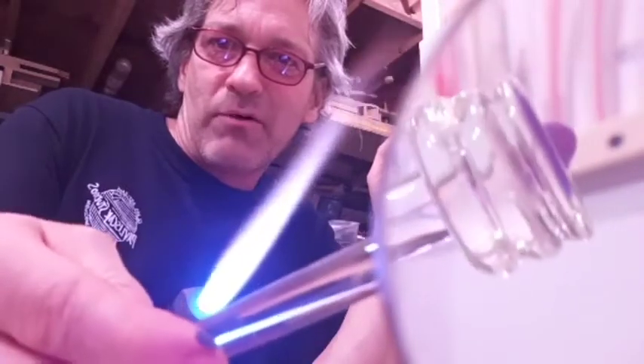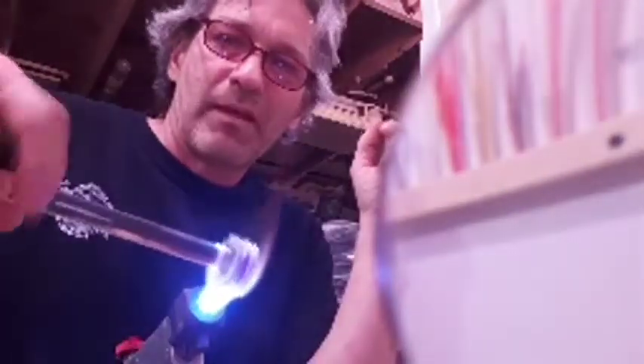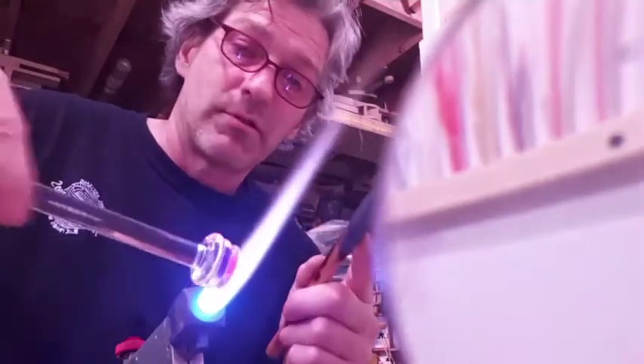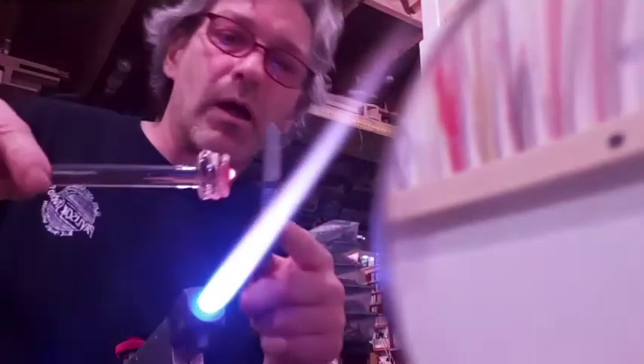And then you see it's bumped out from the surface. So let's heat it, and then I'm going to push it in a little bit, and then I'll melt it until the edge of the dot fuses with the back disc. If you press the dot in, you're chilling the area where you first hit the dot, and so it doesn't spread out. It stays the shape that you want and the size you want. If you just try to get it in with surface tension, the edges won't be as sharp, and it's going to change size. So sometimes that's good. You can work with that. In this case,